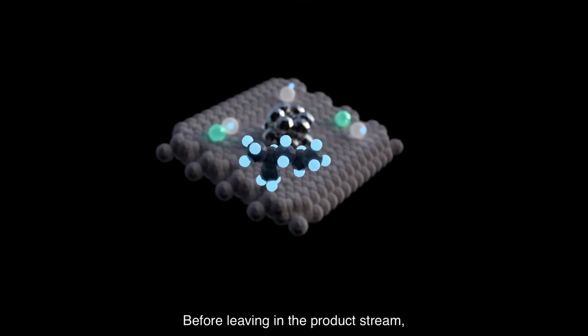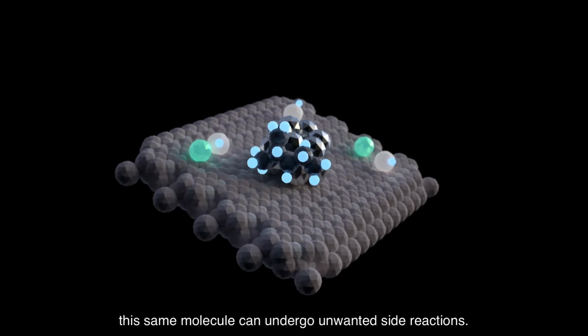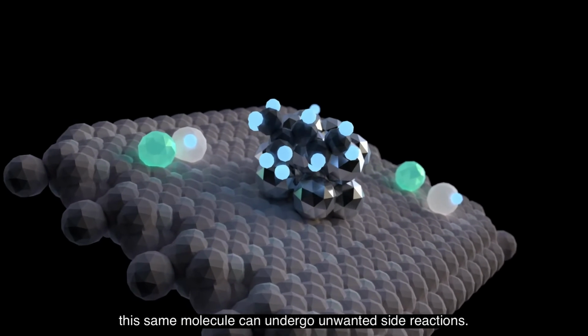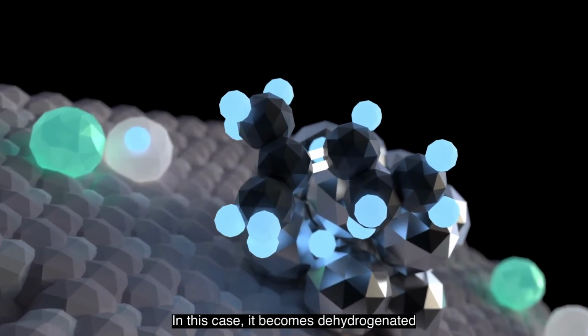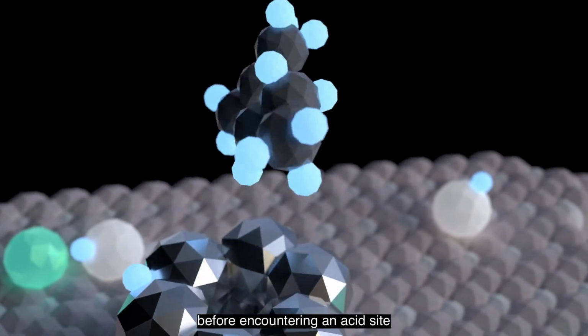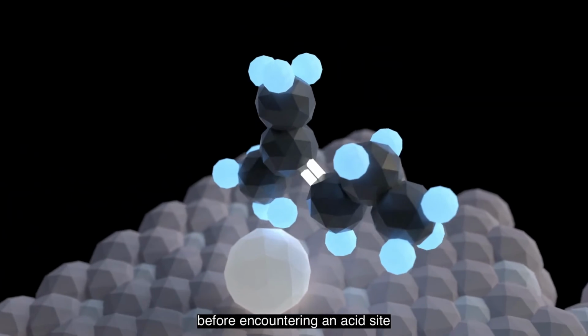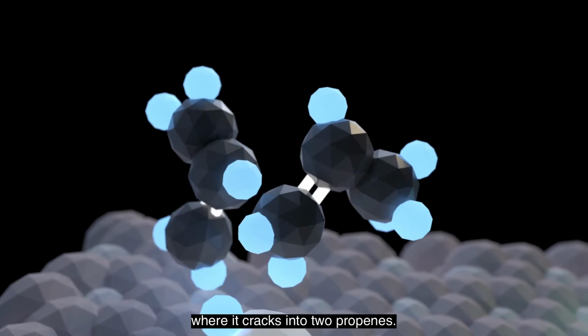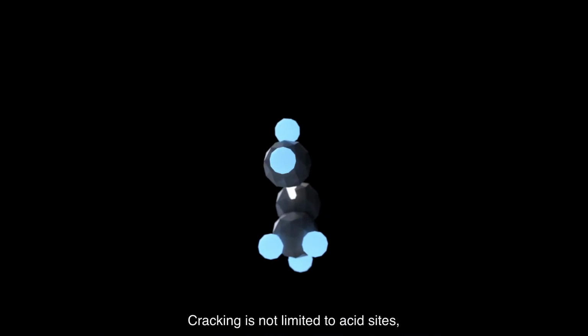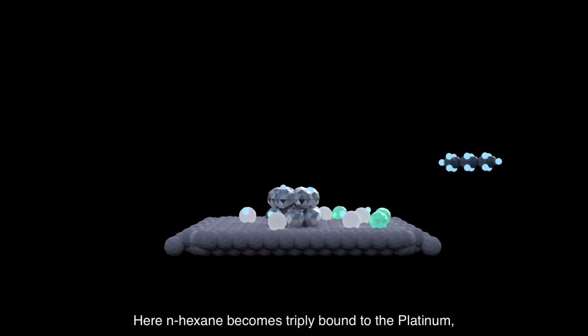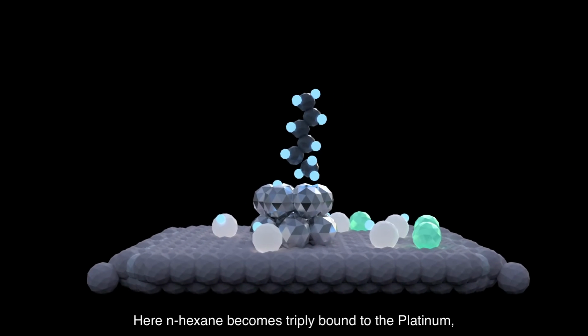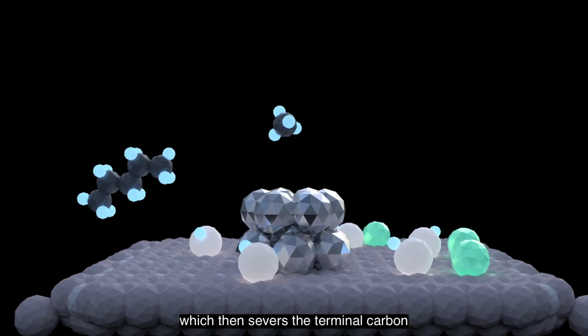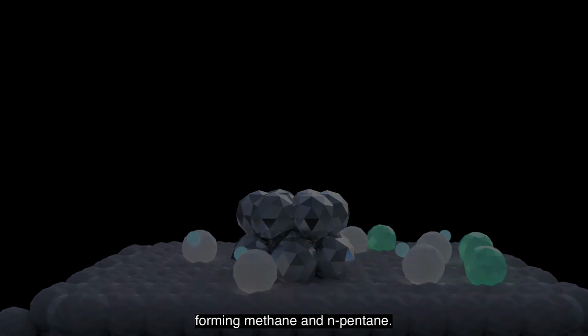Before leaving in the product stream, this same molecule can undergo unwanted side reactions. In this case, it becomes dehydrogenated before encountering an acid site, where it cracks into two propenes. Cracking isn't limited to acid sites. It can also occur on a platinum cluster. Here, N-hexane becomes triply bound to the platinum, which then severs the terminal carbon, forming methane and N-pentane.